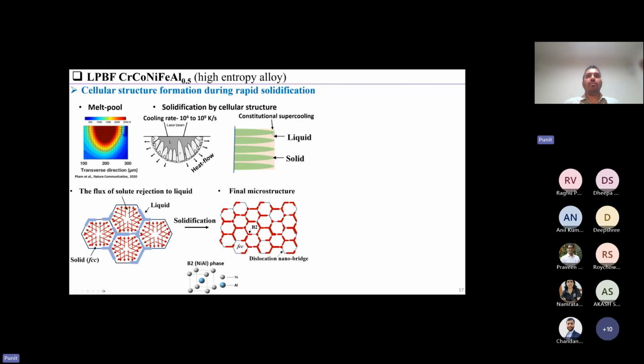And when you have this high concentration of aluminum on these cell boundaries, what will happen is that when they solidify, you might end up forming these B2 phases on the cell boundary. And especially in the regions where you have a flux of solute rejection, the highest flux would be to the cell boundary triple points. And in those regions you will have sufficiently high aluminum to form these B2 phases.